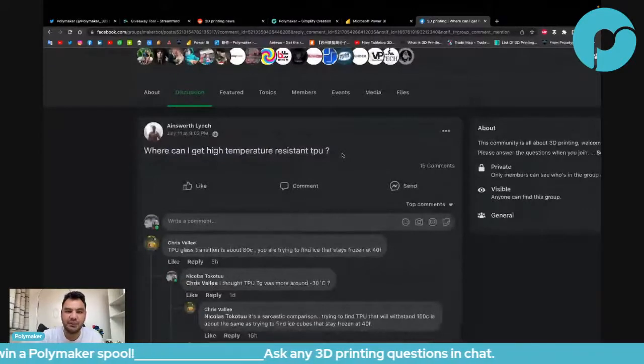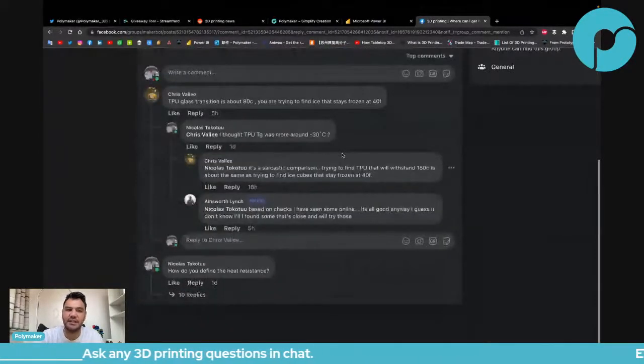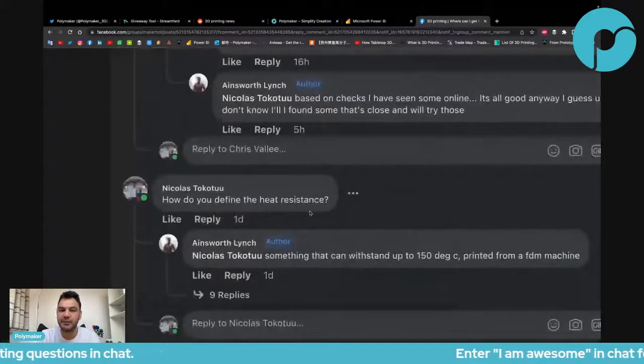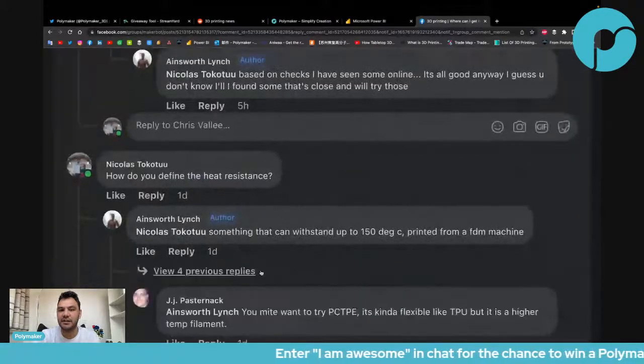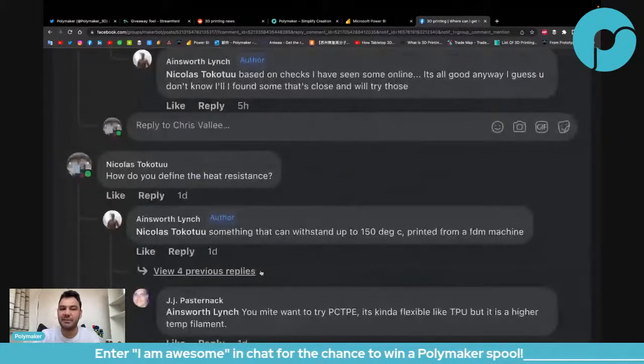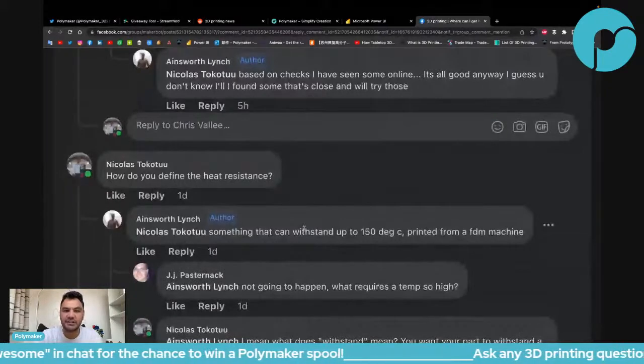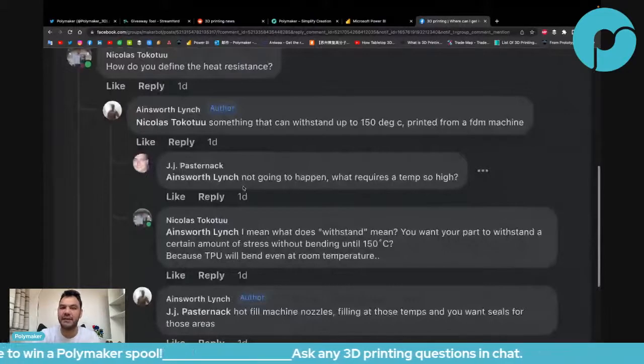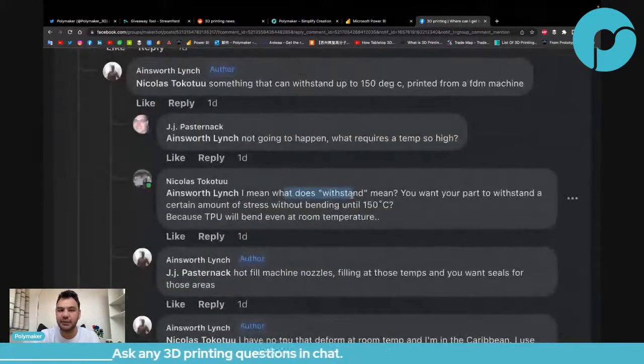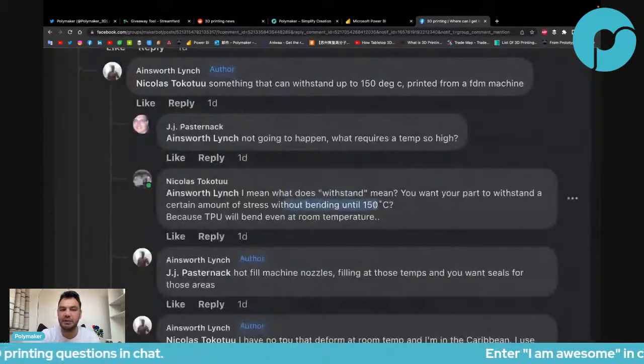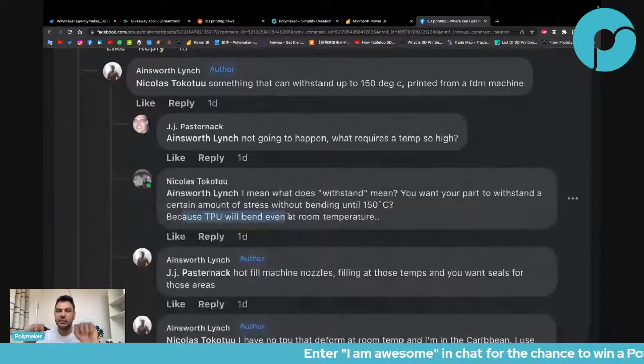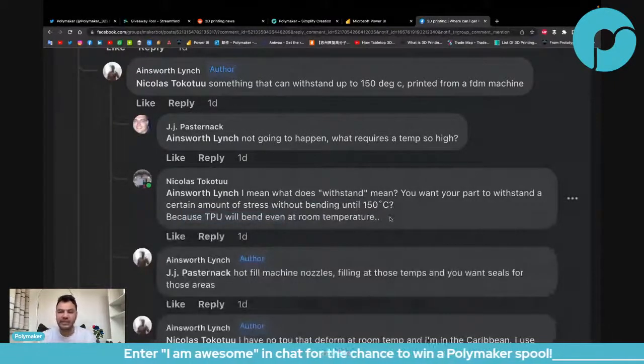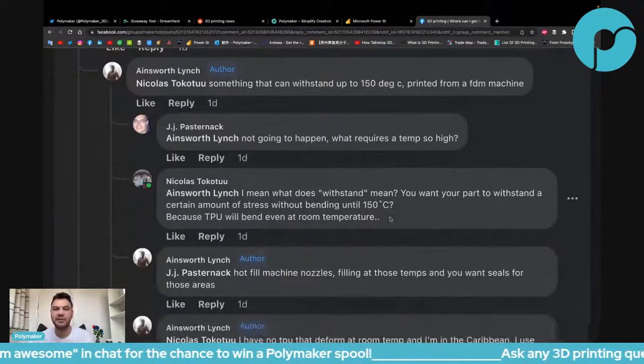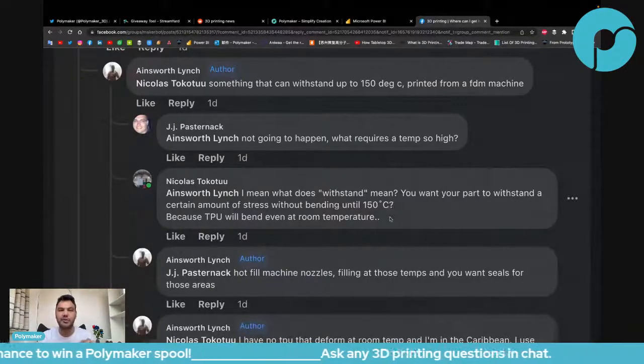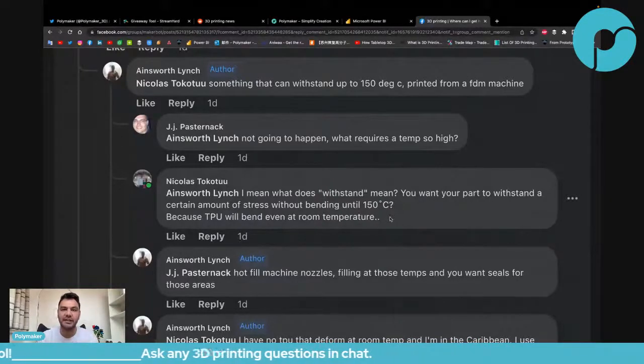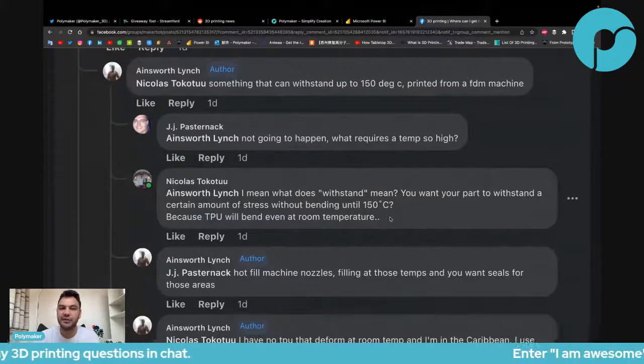So basically what I told him is, how do you define heat resistance? And his reply was something that can withstand up to 150 degrees C. But again, how do you define withstand? I answered, what does withstand mean? You want your part to withstand a certain amount of stress without bending until 150 degrees, because TPU will bend at room temperature. He's talking about something heat resistant that will hold up until 150 degrees. But TPU, even at room temperature, you put a little bit of stress and it's completely bending. So what does that mean, a heat resistance of 150 degrees for TPU?